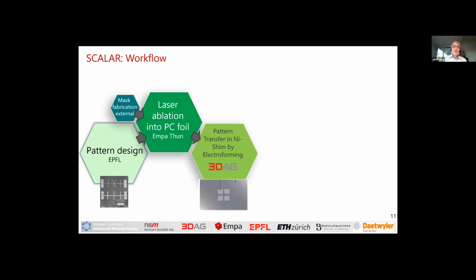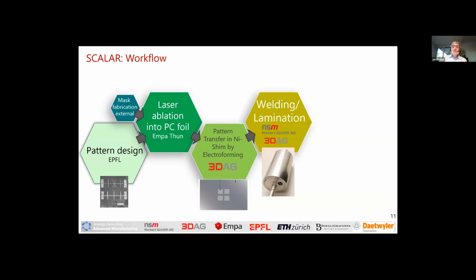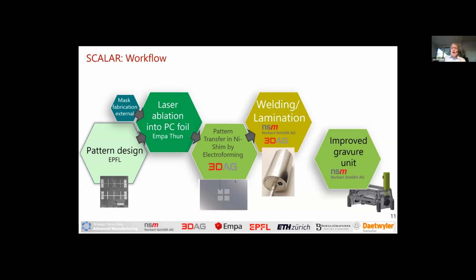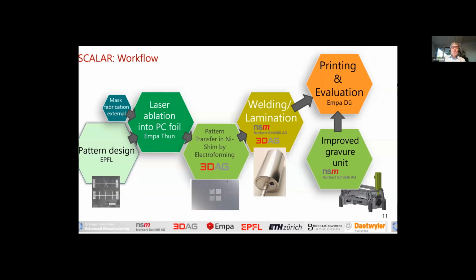So this is done at Empa by high resolution laser ablation into a polycarbonate foil. Then the 3D AG, who are mainly busy with security printing, do a pattern transfer into a nickel shim by electroforming. This one then is laminated and welded onto a gravure cylinder. And parallel to this, what Michael Schläfli also mentioned before, they made some improvements on the software and the hardware side to our gravure printing unit. And then at the end of this project, we're currently doing printing and evaluation of all these different features that we can print with this unit.